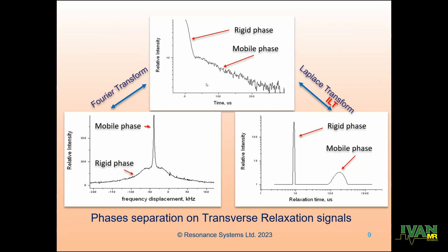And then in time domain NMR, you can also go from this time domain signal to a kind of spectroscopy and observe symmetric spectra. In these spectra, you will see lines that are evenly aligned around zero frequency. You might have something in between that is more mobile, a narrow line, and you might have a wider line that represents the rigid phase. We will talk about this wide line in more detail in just several slides. And here, you can also do some inverse Laplace transformation and get the distribution of relaxation times.